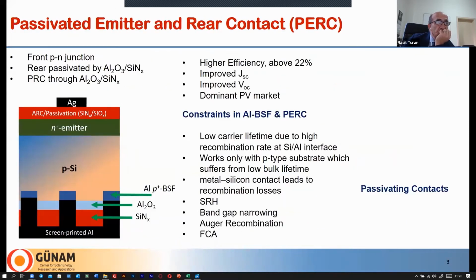An alternative and successful solar cell to the aluminum back surface field is the passivated emitter rear contact solar cell, or PERC, which is also fabricated on P-type wafer. The front side is formed by phosphorus diffusion, and the rear side is passivated usually by atomic layer deposited aluminum oxide, followed by capping by silicon nitride. The rear contact is local with only a few percent of opening, followed by aluminum screen printing to form local aluminum back surface field here.